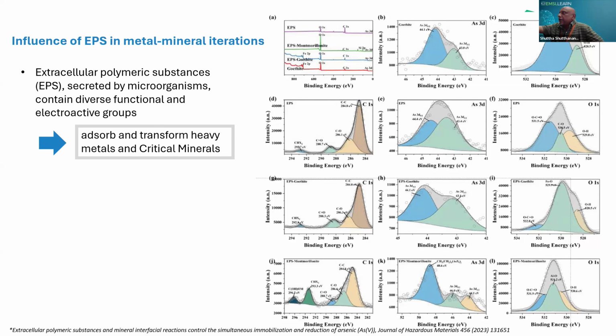But if you look at both EPS and the goethite mineral surface exposed to the arsenic, if you look at the count rate, it is almost 30% less. So less arsenic is binding to this particular complex, but at the same time, it has more arsenic 3+. So as you can see, the EPS is influencing the adsorption of metals on these mineral surfaces.